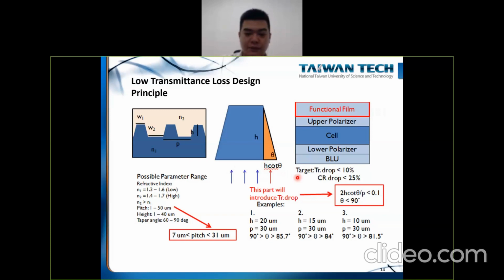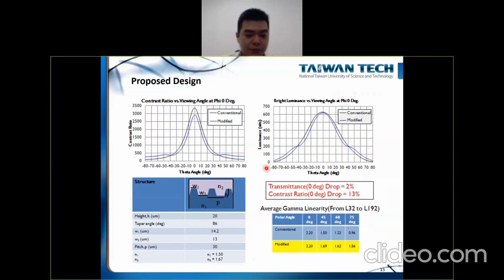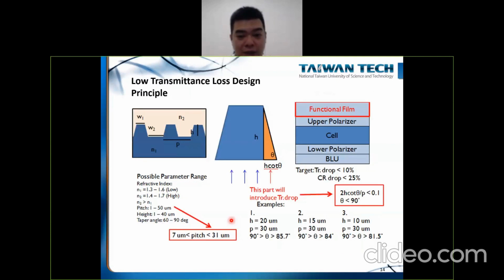So we come up with our optimized structure, by designing a structure with a height of 20 micrometer and a taper angle, which is the angle of the sidewall of the trapezoid, of like 86 degree. 86 degree is this theta angle.